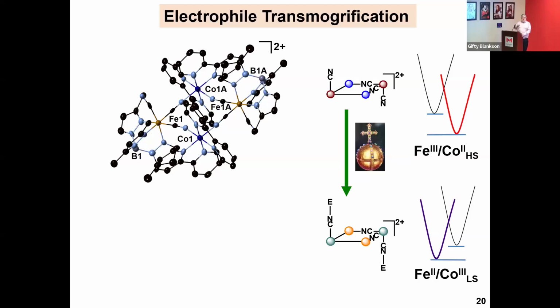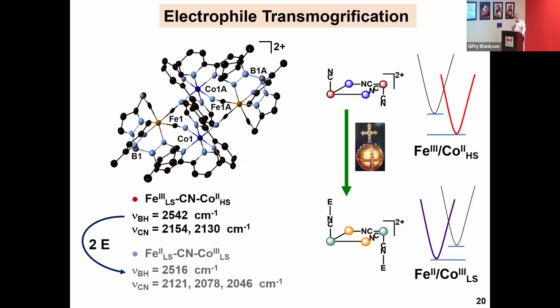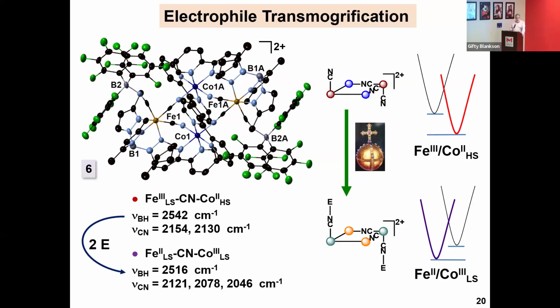And now if you remove that electron density from the cluster, you make it favorable for electron transfer to happen from here, and then down there, and then you get the iron 2, cobalt 3. All right, summarizing a lot of painful data acquisitions and experiments, you do see corresponding changes in the infrared spectra. When you add 2 equivalents, you have to have 2 equivalents of electrophile, else it decomposes. And there's an X-ray structure confirming that we have 2 electrophiles per cluster.